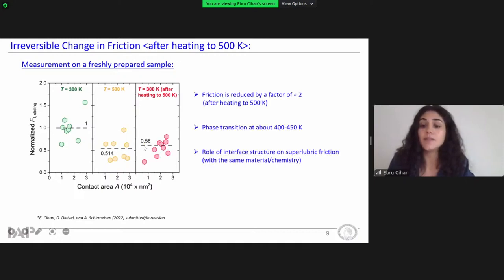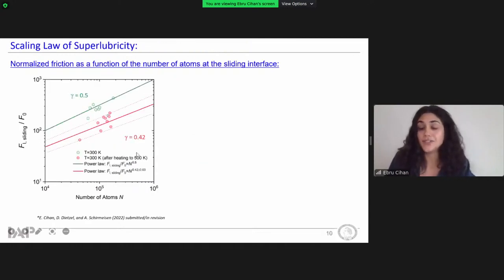As a result, these experiments confirmed previous observations. As you can see, friction is reduced by a factor of about 2 when heated to 500 Kelvin, and this friction change is found to be irreversible, since the same level of friction is measured after cooling back to room temperature. So before I finish, let me quickly relate this friction change to the scaling of superlubricity. If we fit the data we obtained at room temperature before any heat treatment with a fixed scaling factor of 0.5, we obtain a reduced scaling factor of 0.42 for the data we obtained at room temperature after heating.